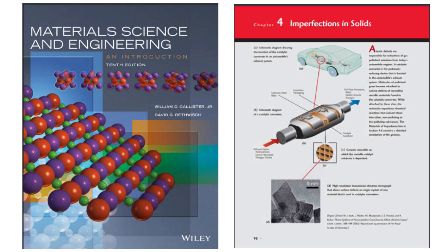Okay, now I'm really interested. How do those tiny imperfections on a surface help a chemical reaction go faster? So those imperfections, things like steps and kinks and vacancies, even those unsatisfied bonds we were talking about, they create these things called active sites on the catalyst surface. These active sites are like little pockets of high energy where molecules can bind and interact more easily. So it's like the imperfections are setting the stage for a molecular meet and greet, where reactants can bump into each other and do their thing.